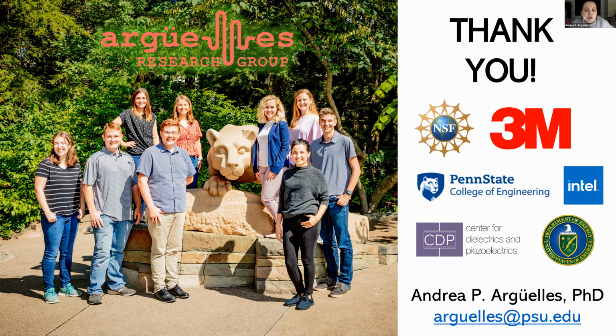That's a good question. Roughness in general is an important parameter to consider. At the frequencies that we were dealing with, relative to the roughness we knew these samples to have, it wasn't a significant factor. We started with hand-polished samples, so we weren't dealing with significant porosity or significant roughness. We wanted to eliminate that factor from our analysis. We are actually in the process of figuring out how precisely we can correct for roughness in the type of attenuation measurements that we're doing. So stay tuned for that.